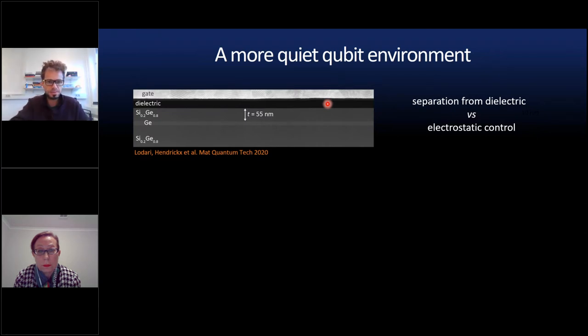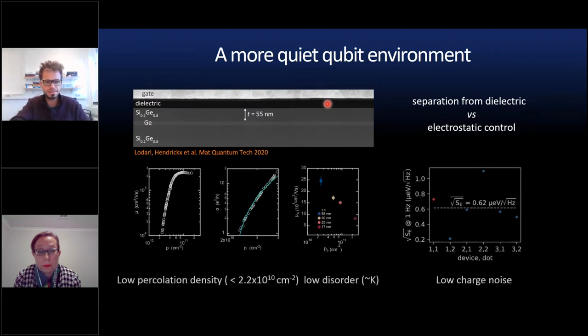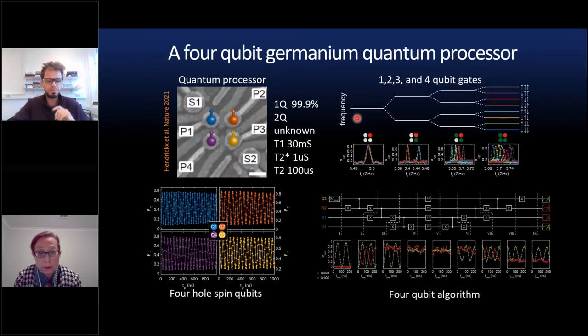So we find this sweet spot at around 50 to 60 nanometers, where we still have a very good mobility, around 200, 300,000. But most importantly, we have a very low charge noise measured in quantum dots, because we are moving away from the interface. And with these improvements in place, we were able to move to a 4-qubit quantum processor, which we published this year. Again, you see the very fast progress enabled also by the material development. And this sets the state of the art with all kinds of semiconductor spin qubits. You see here the 4 qubits, the Rabi oscillations. Again, you can see the quality compared to the previous ones of all 4 qubits individually.